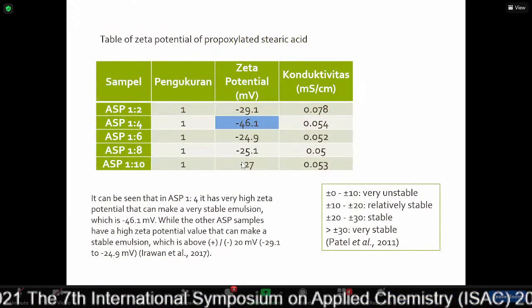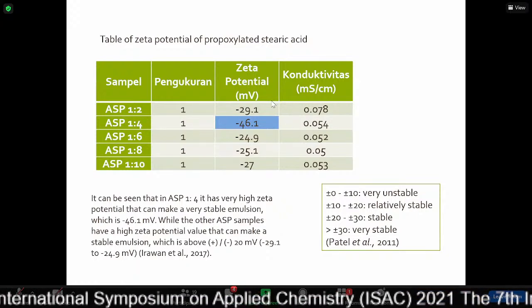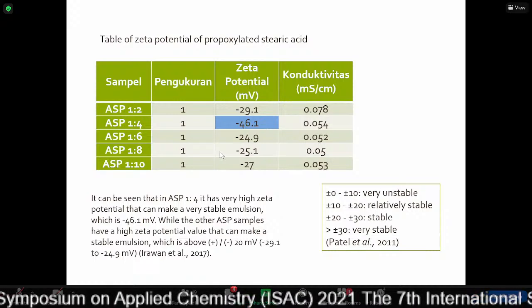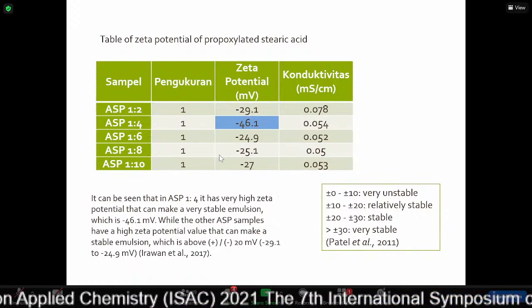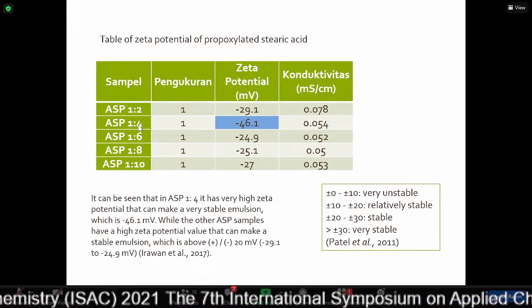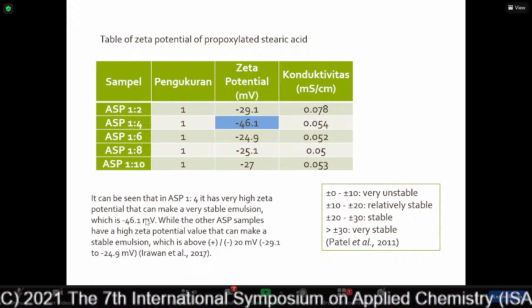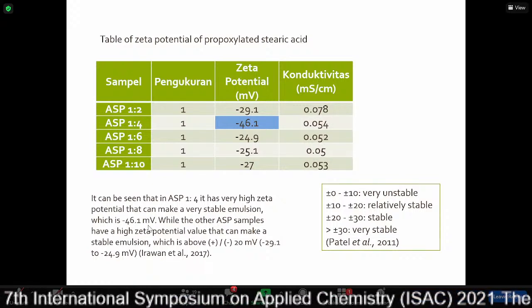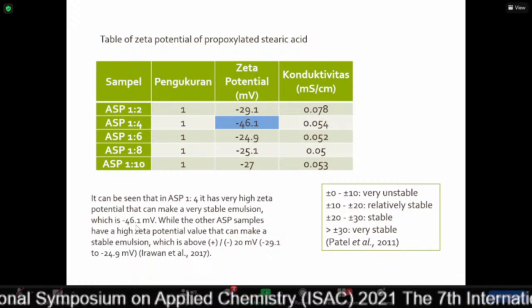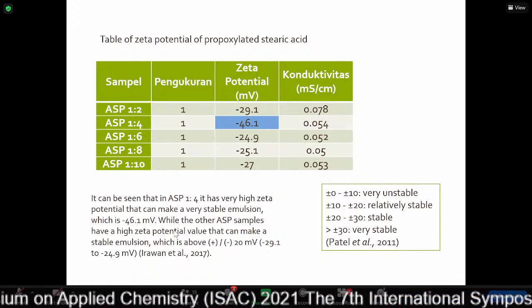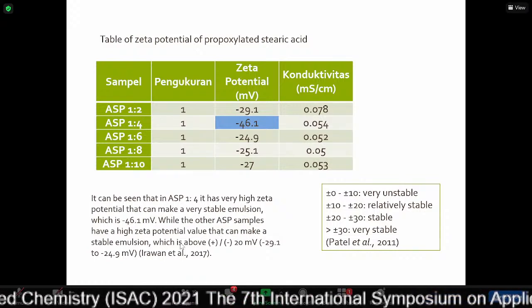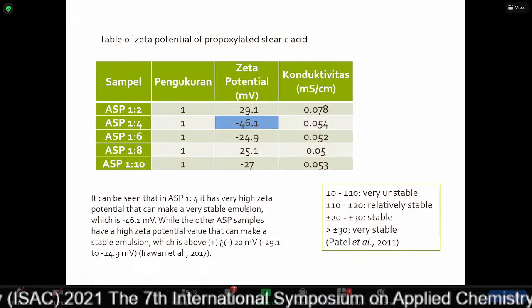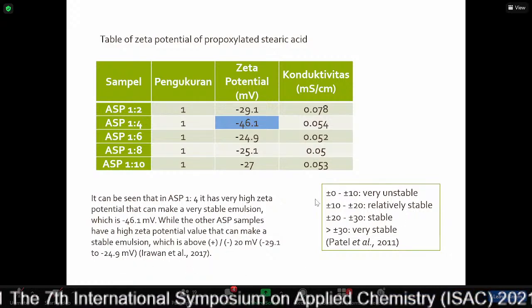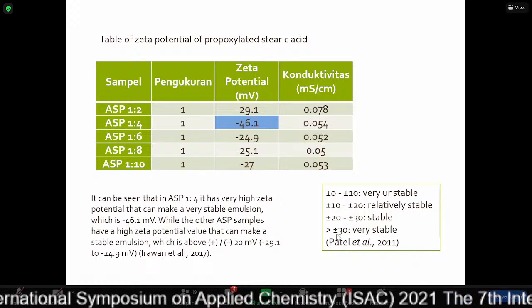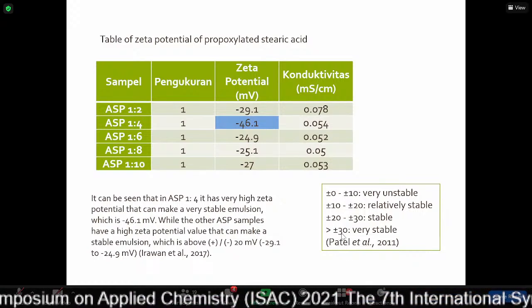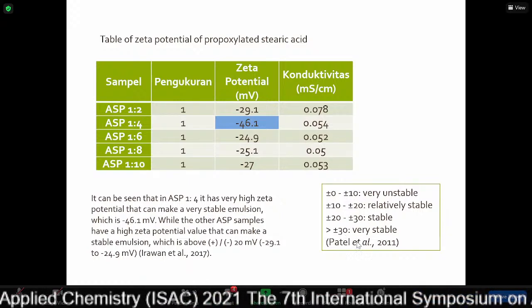This is the data for the zeta potential of the propoxylated stearic acid. We can see here that the stearic acid propoxylation with the ratio 1:4 has a very high zeta potential that can make a very stable emulsion. The result is minus 46.1 millivolt, while the other polymeric surfactant samples have a high zeta potential value that can make a stable emulsion. This is the range for a stable emulsion. When it is more than 30, it indicates this polymeric surfactant is very stable.